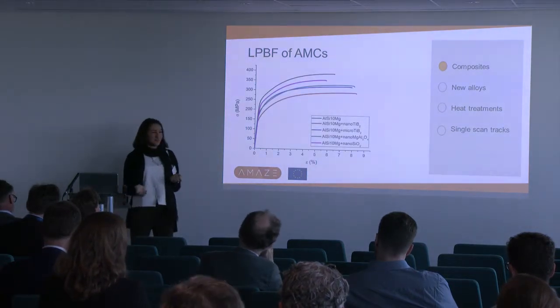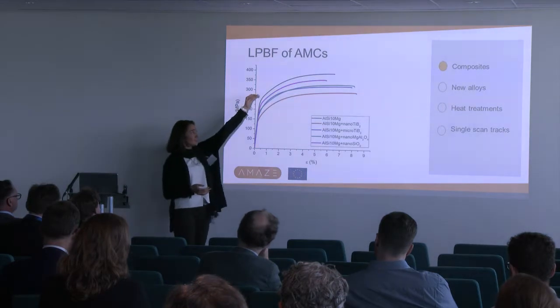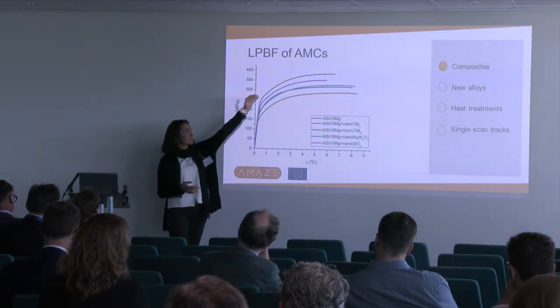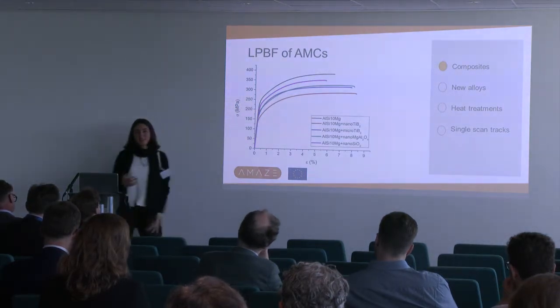And what we observed, unfortunately, was that this is the curve of the aluminum silicon 10, so of the matrix, and all the curves below belong to the composites.